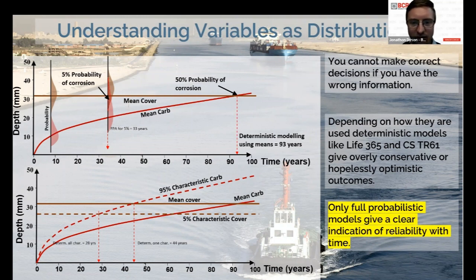To explain that a bit more, take the graph up the top. In this example you have concrete cover data, and you have some carbonation depth data for your concrete structure that is of a certain age. If you just use the mean cover and the mean carbonation depth in the modeling, that would be deterministic modeling, and you would end up with a remaining service life of 93 years. So 93 years until the mean carbonation depth reaches the mean concrete cover depth.